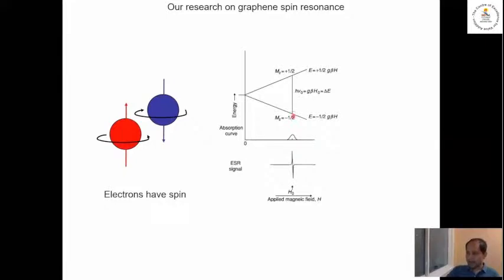So then the idea is that you take some of these electrons in graphene or some material like this, put it in a magnetic field, create these levels, and then you apply microwave radiation, and then you induce a transition from, say, a lower level to upper level, and vice versa, right? And so this would be called a spin resonance, because you're essentially flipping spin with your electromagnetic waves.